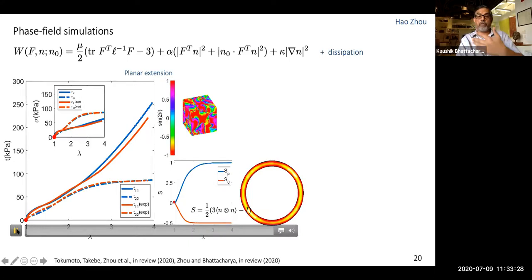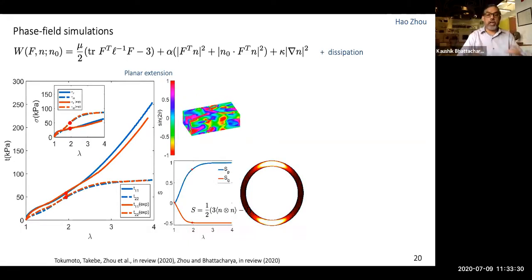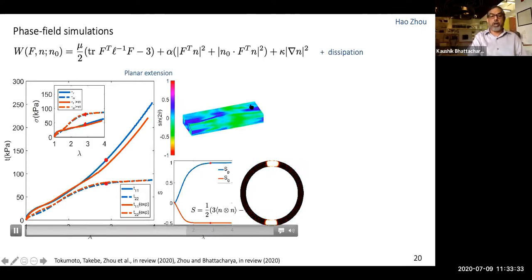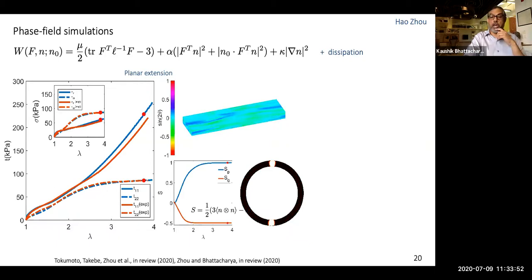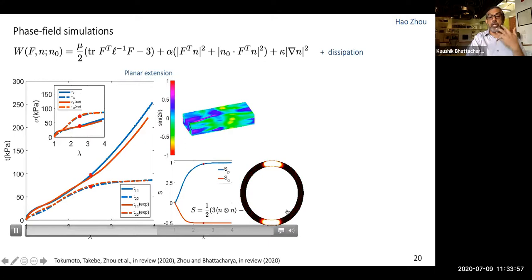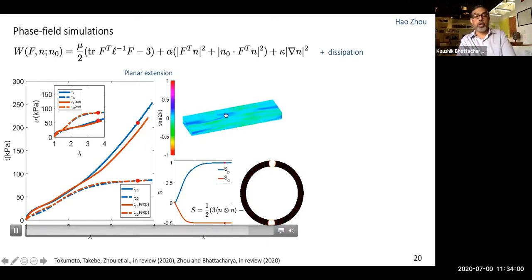So to describe the full behavior, we go back to our original energy with all the non-ideality, and you can do phase field simulations of these. And here's a case of planar extension. You see how the microstructure is evolving, and you see the state of stress. Here you're seeing both the computed one and the experimental one. And you see that with just 5 parameters, you can describe a whole range of behaviors very well. What you're seeing here is the Young measure. It tells you the distribution, some average, the statistics of the distributions of the directors that you're seeing here.